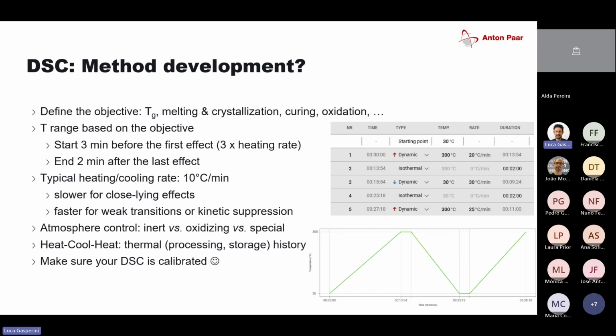I have two time details there: start 3 minutes and end 2 minutes before and after the last effect. Why do I do that? We need to achieve a certain portion of the DSC signal before the effect actually happens to record a baseline. And very similarly, after the effect. That means I need to see the DSC signal where no effects are happening. That helps me then to create the possibility for integrating peaks and analyzing the results, because I want to see nothing before and nothing after.